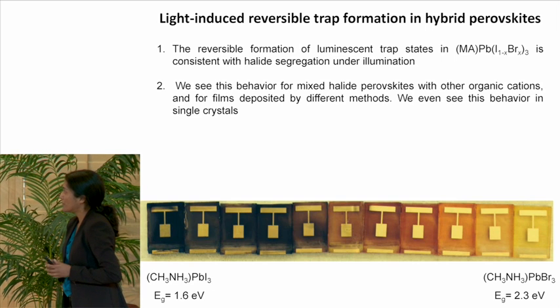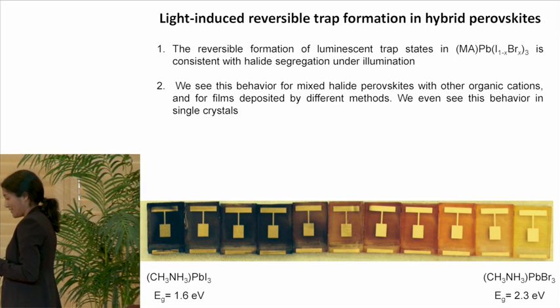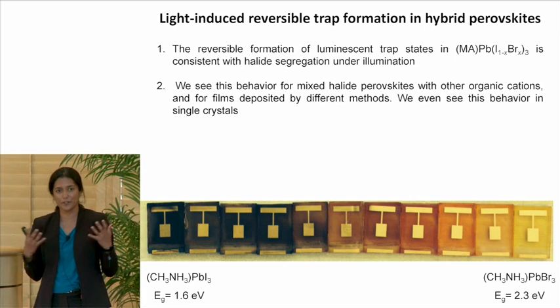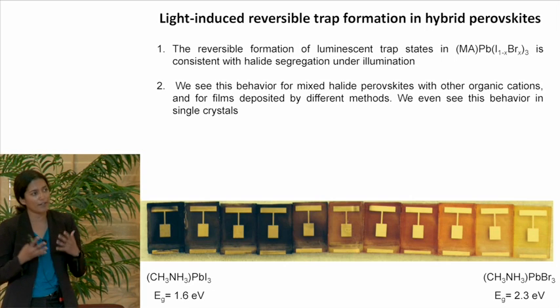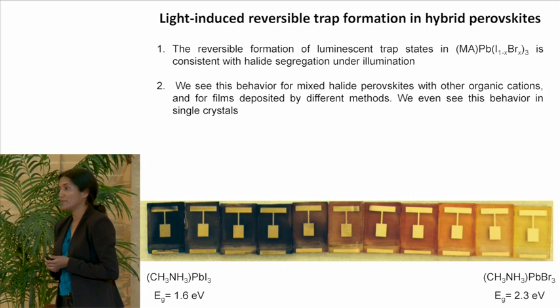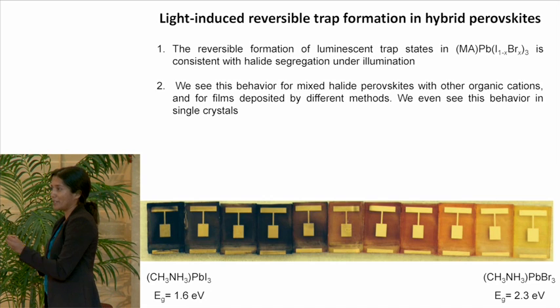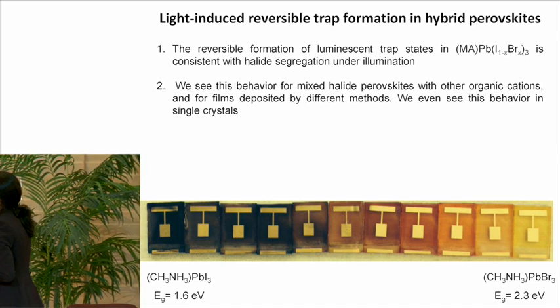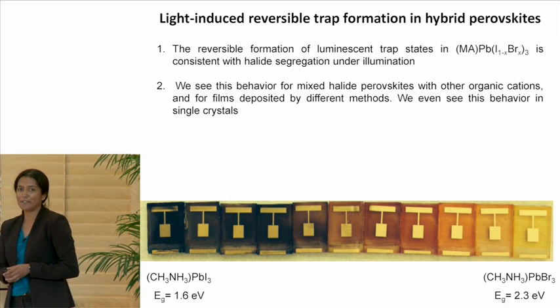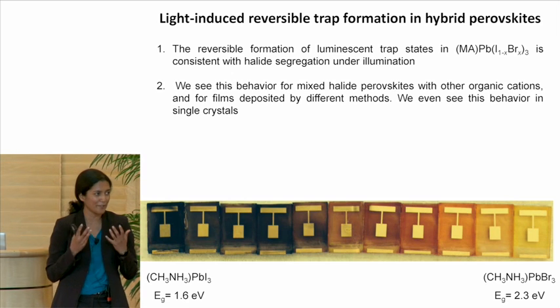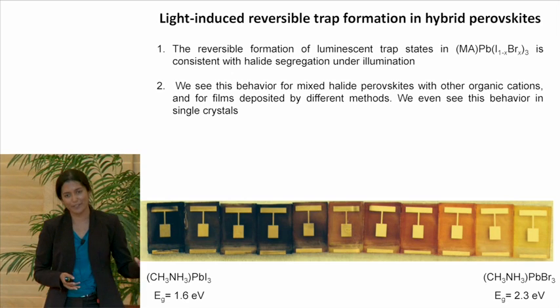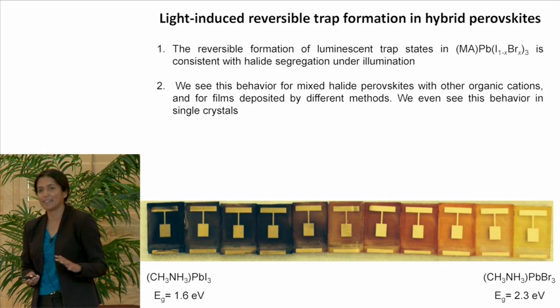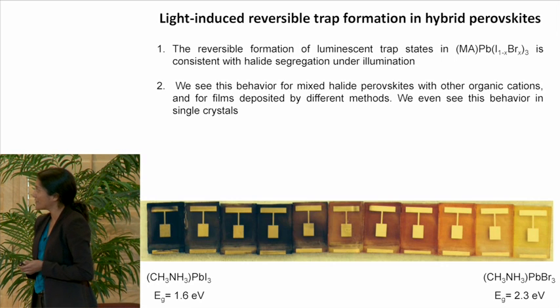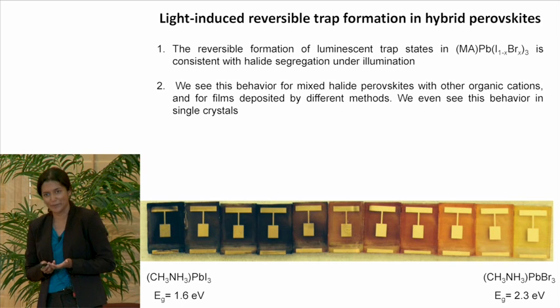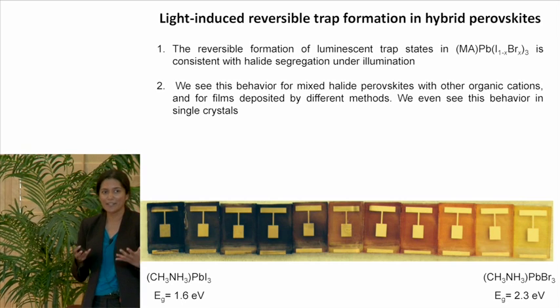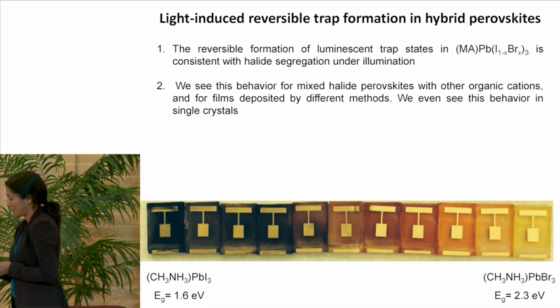So just to end, I want to summarize this section. We see very interesting reversible changes in these materials upon illumination. So far, our observations are all consistent with halide migration initiated by stabilization of these holes through halide segregation. And we see this behavior even if we were to change the organic ions in this material. We see this behavior in films formed through all the deposition techniques mentioned in the literature for making these materials. We see this even in single crystals of the material. So we know it's inherent to the material and not due to any weird surface sites.